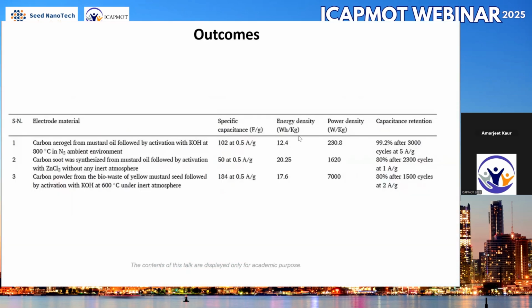If we compare this device with the work of other people on mustard seeds, they have used the carbon soot from the mustard oil directly, rather than obtaining the activated carbon from the skin of the mustard seeds. In any case, if we compare with these biowaste materials, our value so far is better than any other value reported in the literature. There are hardly two or three reports, so our results are more promising. But now we have to develop a commercial grade device out of it.